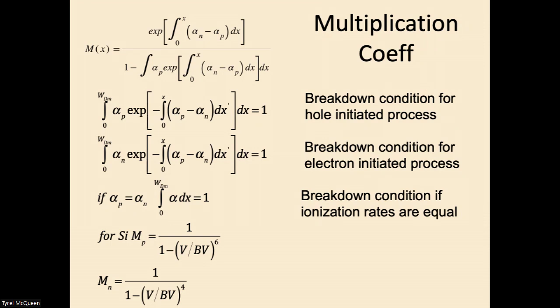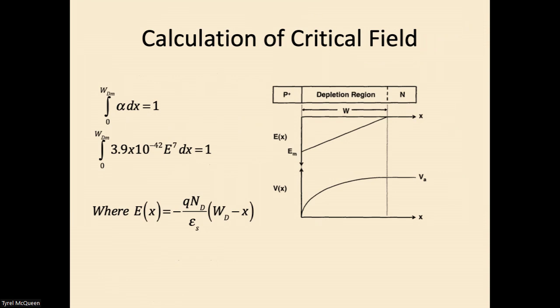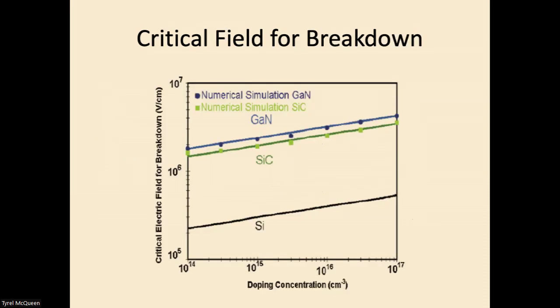Often, we make life easy for ourselves and say, well, maybe these ionization coefficients are equal, and then it becomes a simple integral. For silicon, there are some approximations. So in calculating the critical field, you basically solve, in this simplest case, with the ionization coefficient and the electric field varying in the classical triangular field formation, for the critical field. When you actually do the calculation, you can see that the critical field has some variation with doping, and these are simulations. And here is the critical field of silicon, which again has some variation with doping.